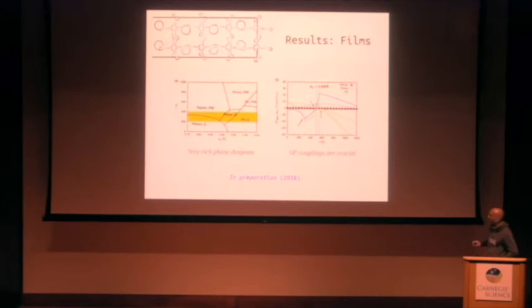the Gibbs free energy balance changes. And we have come up with this phase diagram, which also seems to be very interesting. In particular, we have this section here in which we can go from polar to non-polar to polar again, and even in this region here we also see some kind of reentrant behavior, right? So we can actually stabilize a polar phase by increasing temperature, which is quite uncommon. Again, if you don't take into consideration spin-phonon couplings, you get a completely different phase diagram.